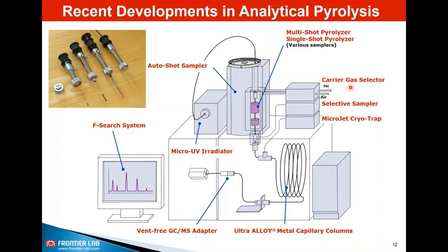And we have this carrier gas selector that allows you to do the pyrolysis under air, then you can do the analysis under helium. Those kinds of things are possible with this carrier gas selector. And we have this selective sampler that allows you to do a hard cut, hard cutting evolved gas analysis GCMS, which I'll be speaking about later today. And this microjet cryo trap allows you to look at very volatile compounds, because you are introducing liquid nitrogen to ensure that you are able to trap all these volatiles in the column before the GC run starts. And we have a search engine, the software that helps you interpret the data efficiently for over 1000 polymers and over 500 additives. And the capillary column is made of ultra alloy metal, which we cannot discuss much today, but definitely we will take an opportunity on some other occasion.